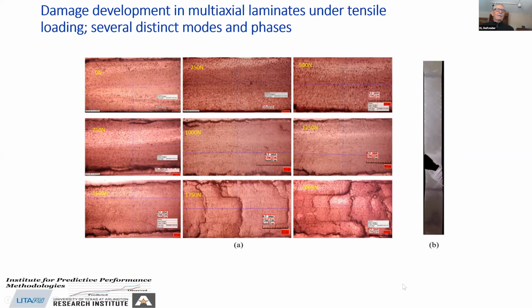This diagram in the left center is an edge replica. These are edge replicas of a sample of multiaxial laminate, which is being pulled in tension. The axis of loading, of course, is left to right. The damage developing through the thickness of these materials is clearly seen. Matrix cracking, of course, in some of the off-axis plies.